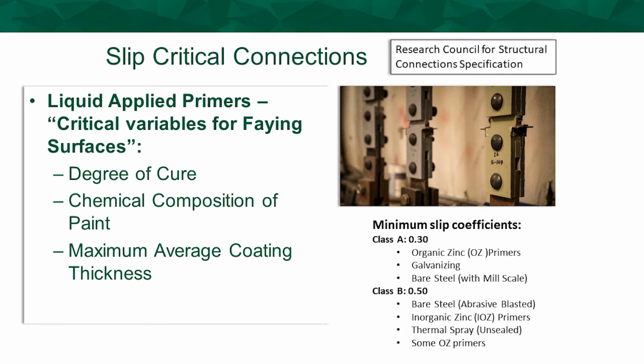You want to make sure that that coating is cured, not just to top coat or to touch, but is actually cured before you pull those plates together. You want to make sure that the chemical composition of the coating meets that slip critical requirement, and you want to understand the maximum average coating thickness allowed for that system to work properly and meet those conditions.